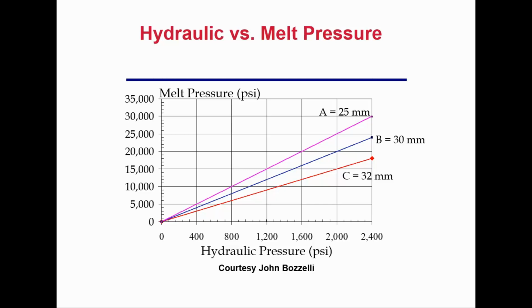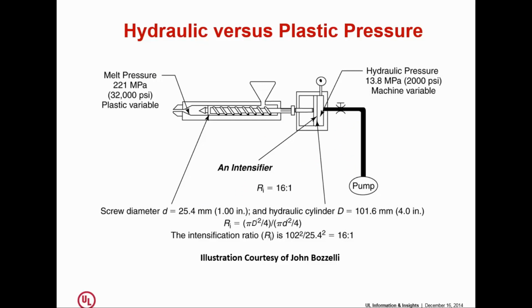That's a pretty big spread, just based on the size of the barrel that you decided to purchase with the machine. Now, this is a schematic that John Bozzelli provided, and you'll see his name quite a bit in this presentation today because John's done a lot of the work on this and has been working on this for quite some time, and encounters this on a regular basis when he goes into plants and finds out that people are running a machine with insufficient pressure to actually make the part that they're trying to make. And the genesis of that is that they do not have a large enough intensifier. The ratio between the area of the ram and the area of the screw is too small. Consequently, the hydraulic pressure doesn't turn into enough plastic pressure. Now, in this case, this is a pretty good machine, 16 to 1 intensifier, so a 2,000 psi hydraulic pressure generates 32,000 psi of plastic pressure. And for most applications, this would be considered an internationally competitive machine.